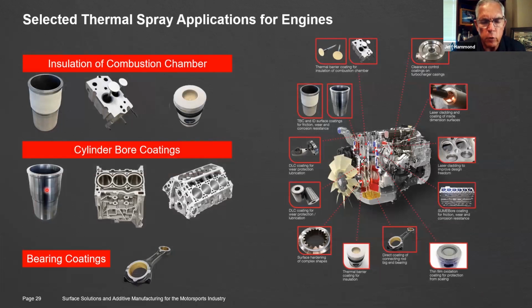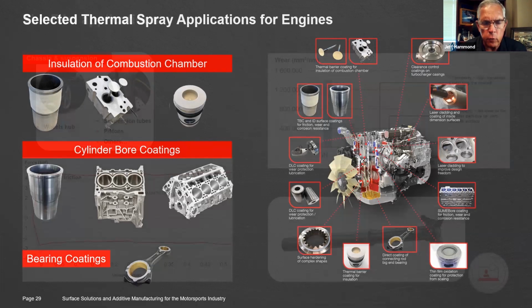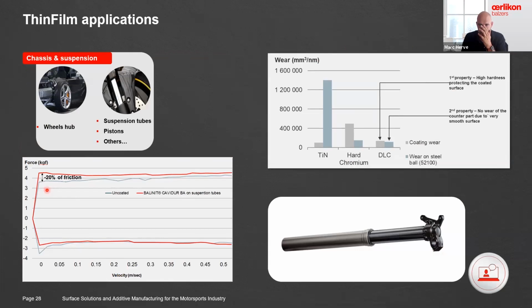Okay, let me interject right quick then. The coating making the difference right there. The 20% reduction in friction, and that correlates back basically to heat, correct? No, it's literally about the interaction between the sealing and the coating. So the 20% is not about the heat. It's really, let's say, the power you need to make things move. Due to the composition of the coating, you have less of the sticking effect that you can get with the seal, for example. And this is why basically you have this reduction. So it's not related to the heat, it's more, in this case, related to the composition of the coating and how it's reacting against the sealing.